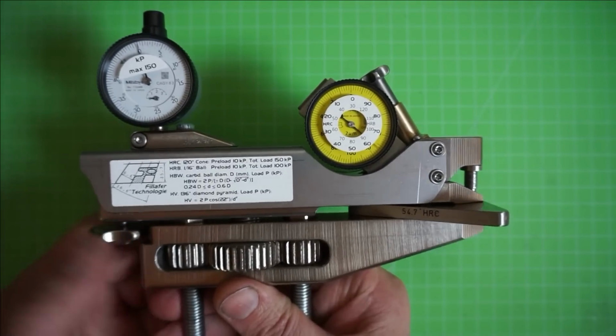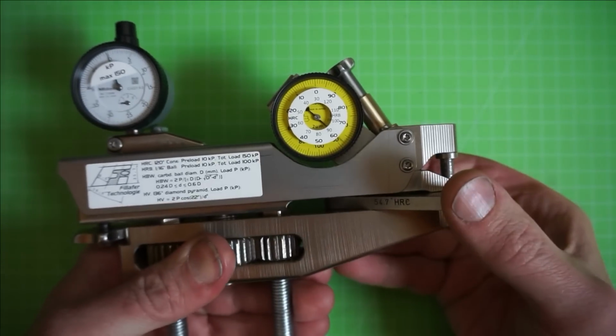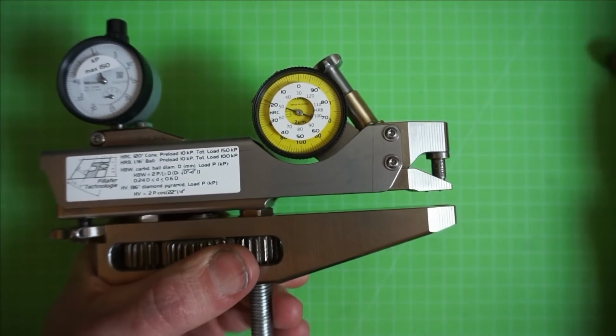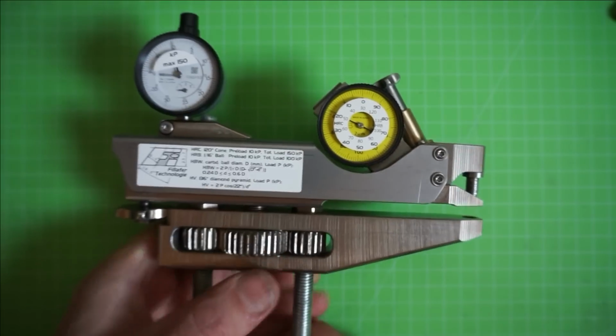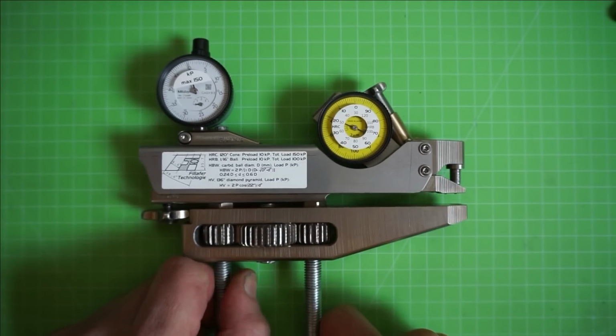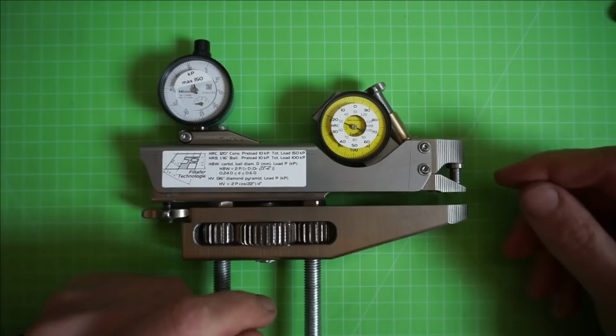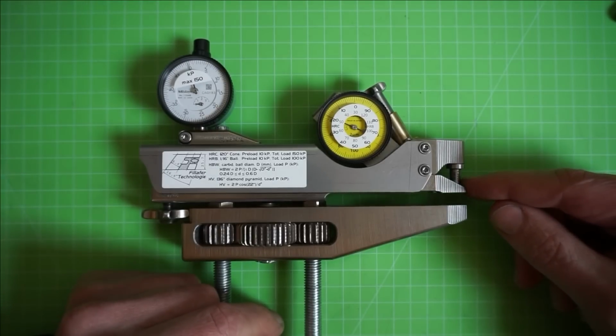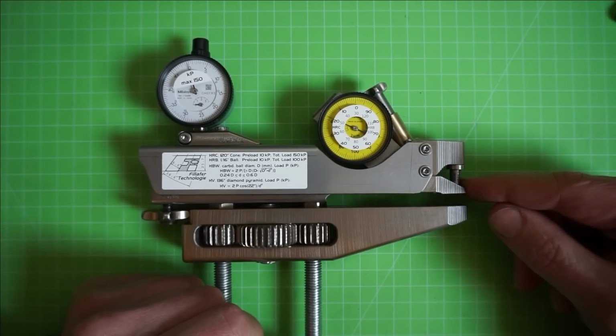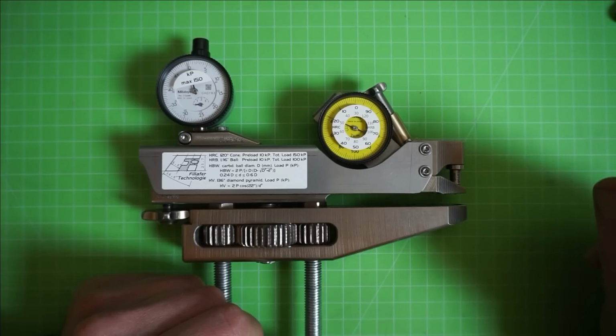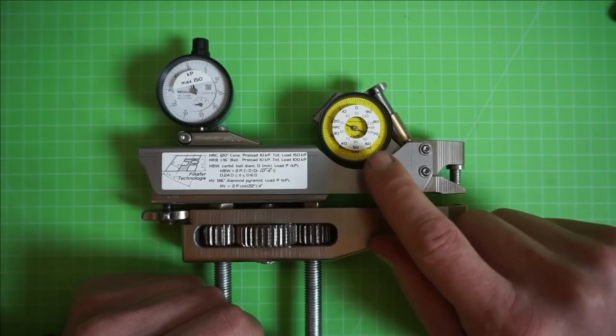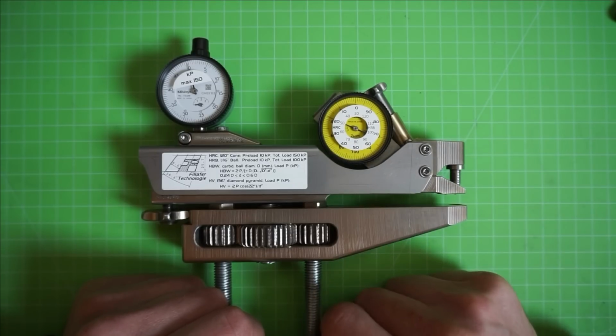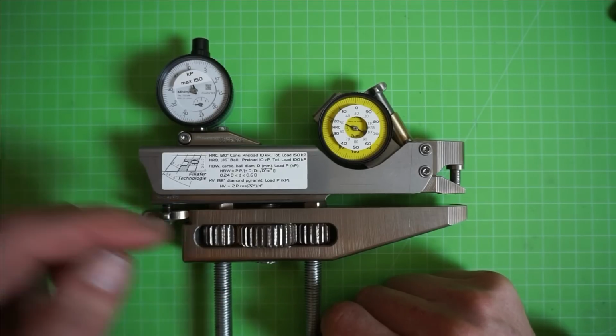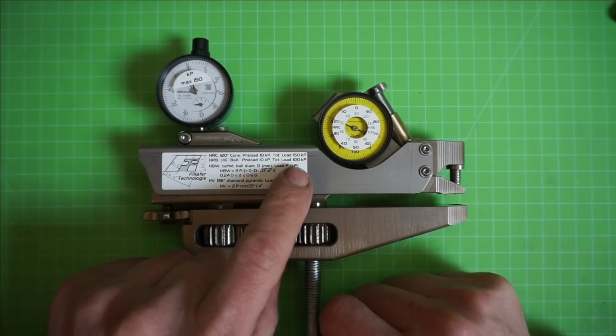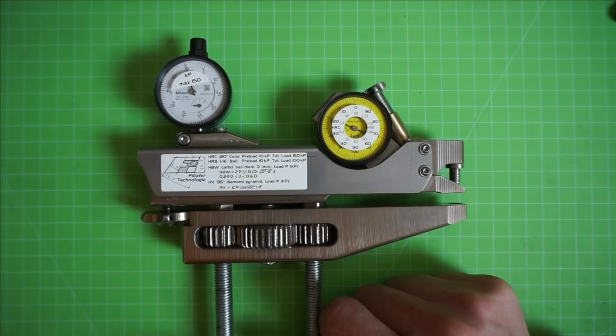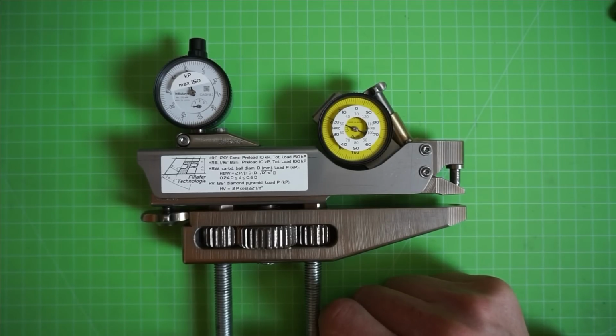Alright, so far as the Rockwell cone method is concerned, the Rockwell ball method for the softer materials works just the same. You only use a different indenter with a tungsten carbide ball of 1/16 of an inch diameter, and you use the inner scale of the white ring. But the procedure is the same, only the total load is not 150 kilopounds but 100.